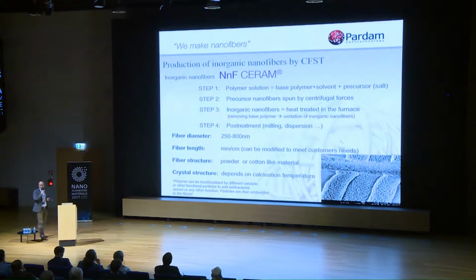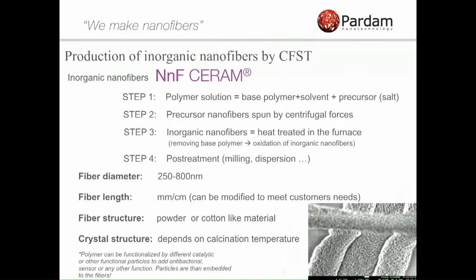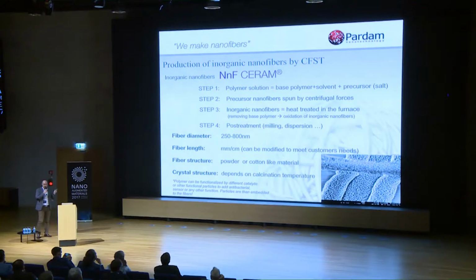So this is actually how ceramic nanofibers are made. This is a step-by-step process description. In the first step, we prepare polymer solution. We get base polymer, we dissolve it in solvent, we add precursor in a form of salt or colloid suspension. We mix it together and we prepare solution of certain concentration and viscosity. Then we use centrifugal forces to spin what we call precursor fibers.